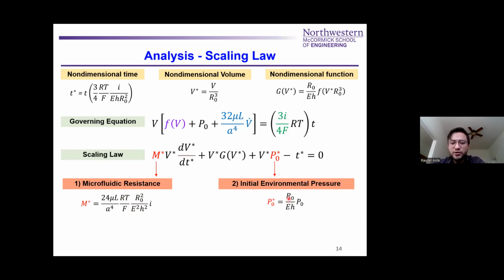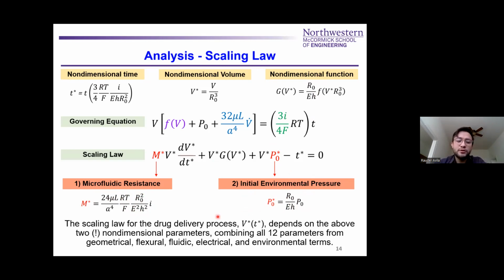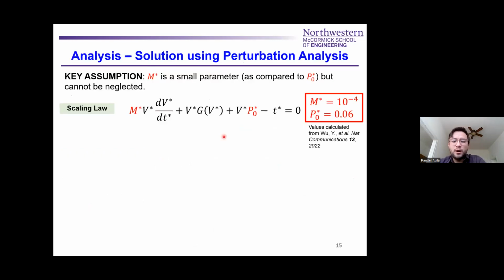And then on the other side, we have the influence of the environment. This pressure term is also normalized in the same way as our non-dimensional function. So we have the radius over the modulus times the thickness, and then we have our dimensional pressure here. Now these two parameters control the delivery process of our system. So in our scaling law, we go from about 12 parameters to only 2 that group geometrical, flexural, fluidic, electrical, and environmental terms.